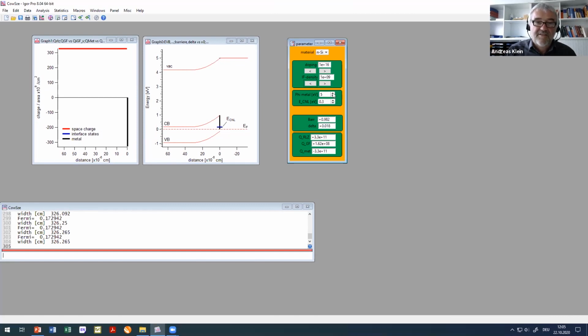If we change the work function of the metal now, you see that there isn't any interface dipole potential, and there is also no interface density, no interface charge. So now the barrier height is directly following the work function of the metal.